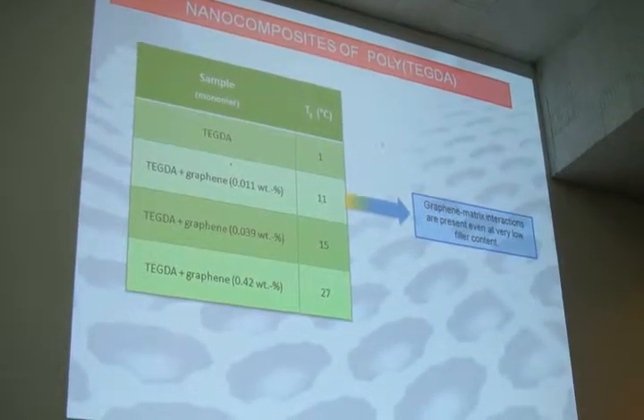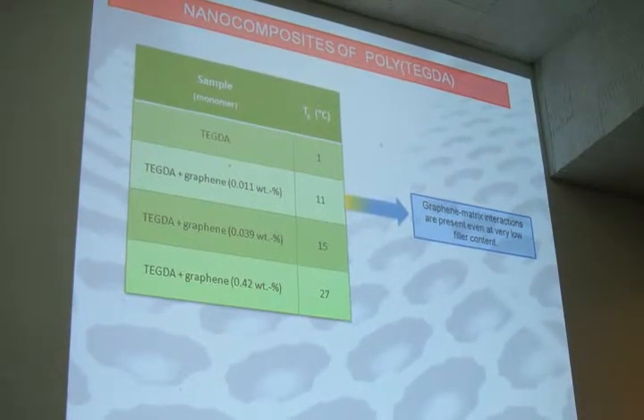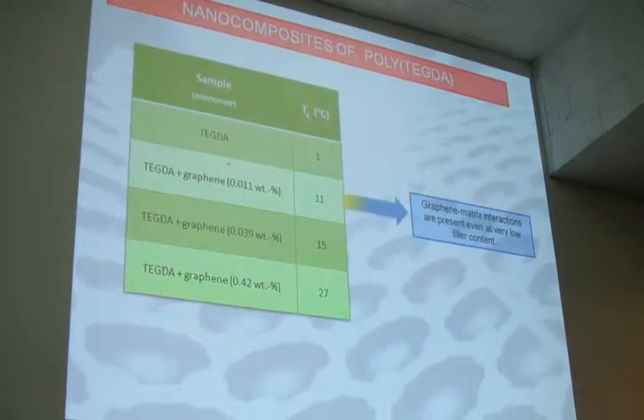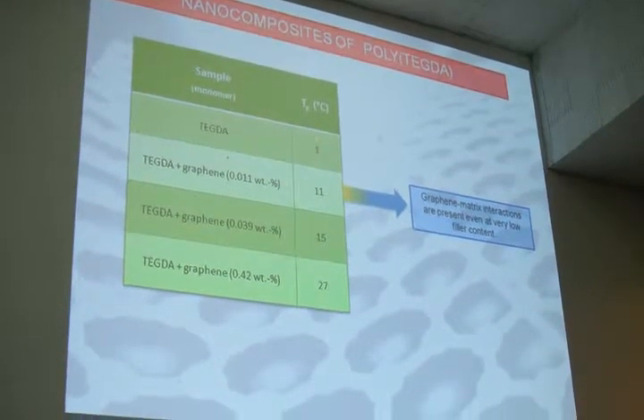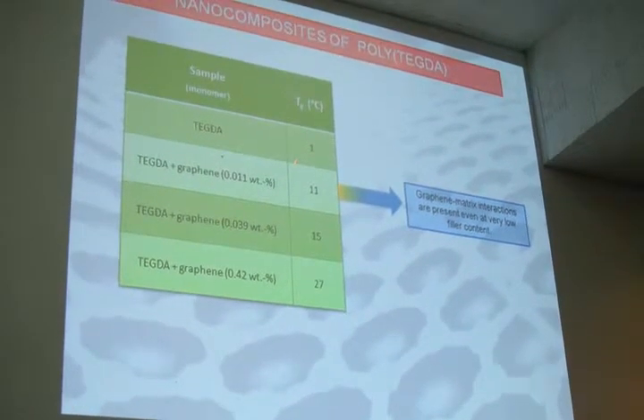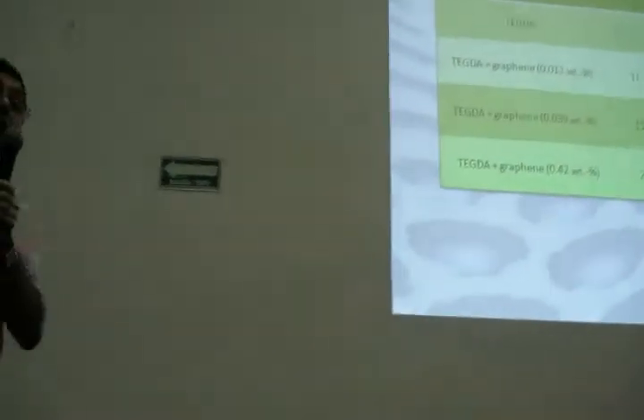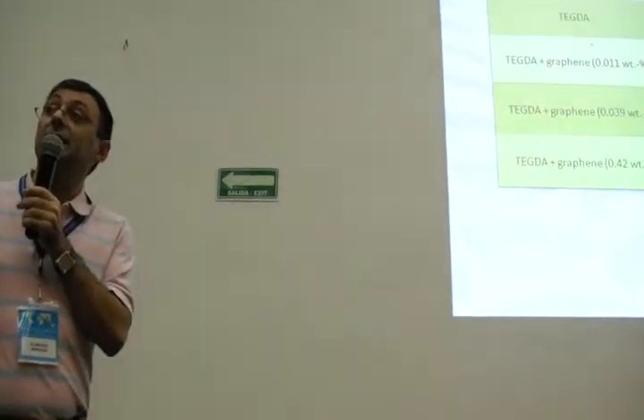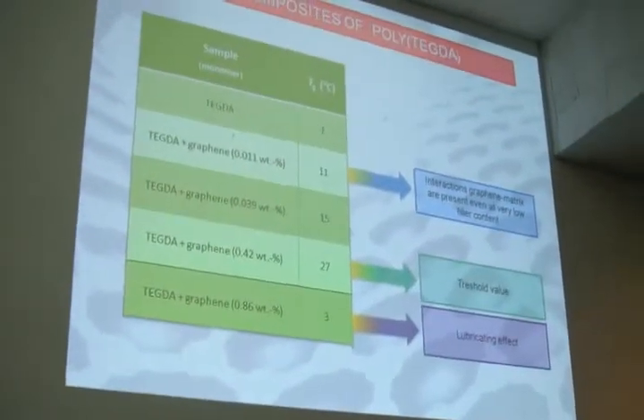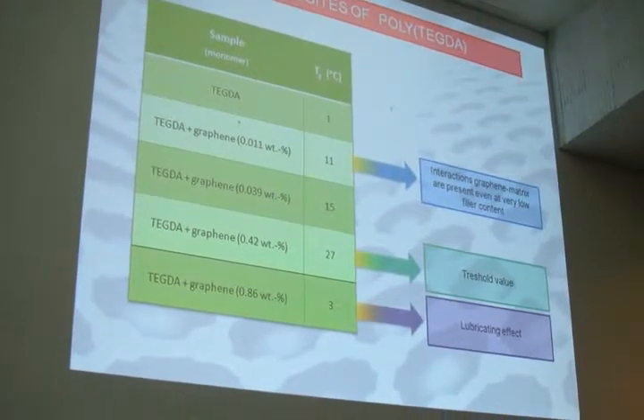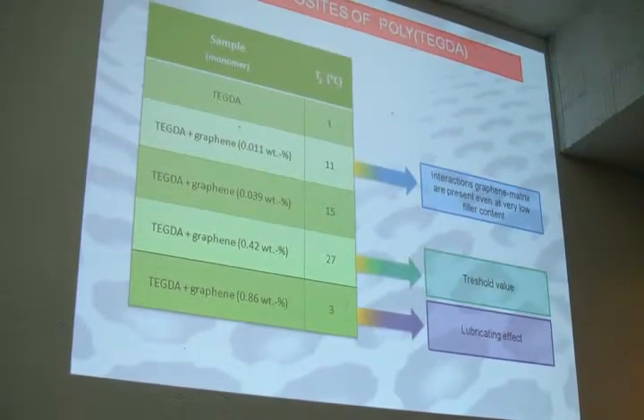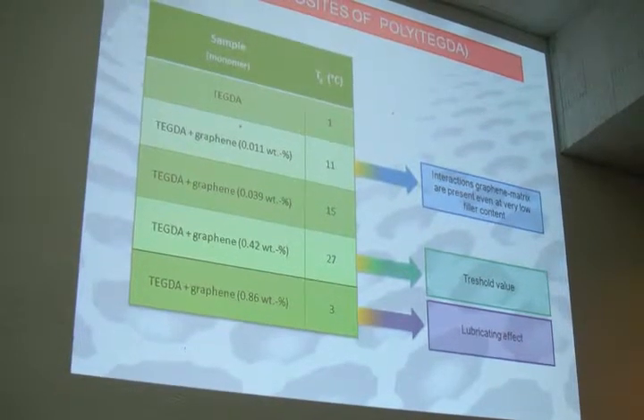And what about the properties? For example, glass transition temperature. The neat polymer is characterized by a glass transition temperature at about 1 degrees. But if you add graphene and increase this amount, you have an increase of the glass transition temperature up to 27 degrees. But after that, you find again a threshold value. After that, you have a decrease of Tg, as in the previous case.